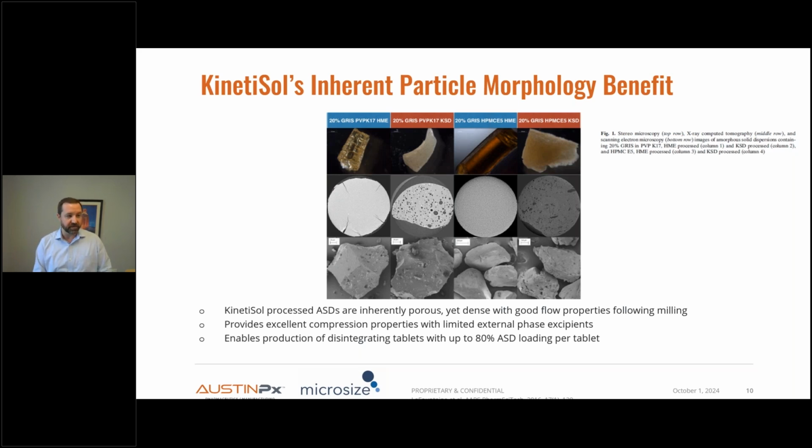There are inherent particle morphology benefits. In one of the earlier slides, I listed potential CQAs as manufacturability and compressibility. We've demonstrated through a variety of studies that KinetiSol processed ASDs, due to the nature of the mixing and the quenching process, produce dense and good flowing particles, but there is some residual porosity that provides excellent compression properties. And so this allows us to make a denser tablet with more drug, a higher payload per se, so that we can reduce the total pill burden and total tablet size that the patient ultimately sees.